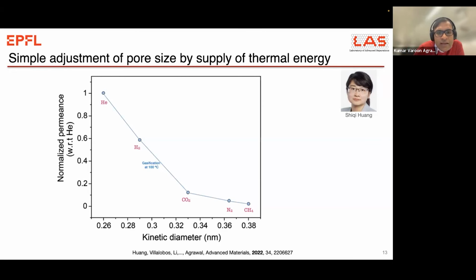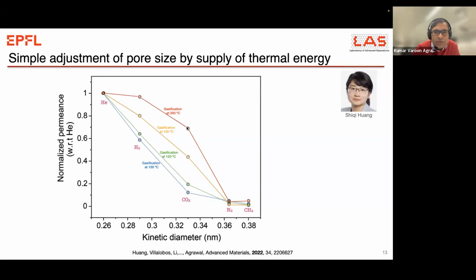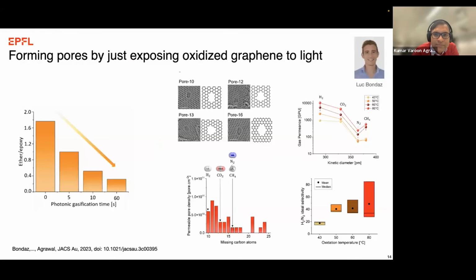All right, so then we can increase the size of the hole by heating it to higher and higher temperature. So this is heating to 120, 150, and 200 degrees C. And what we can see is that now CO2 starts to come faster as well, because the hole size has expanded. So the energy barrier for CO2 to cross the pore is less, and so it can permeate faster. And we can control it in a way that nitrogen doesn't go through, so you can get CO2 nitrogen selectivity.